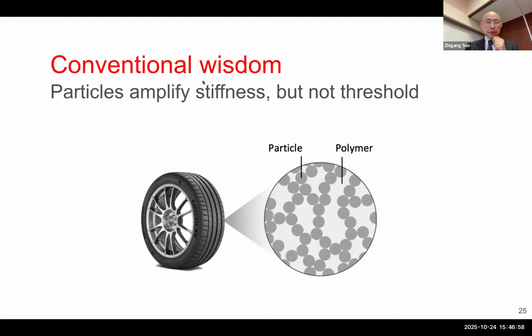So conventional wisdom: the tire is a composite of a polymer and hard particles, typically carbon particles. The particles greatly amplify stiffness, make it stiff. That's true. But not fatigue threshold. People had decades of data to show fatigue threshold stays at about 50, maybe 200 joules per meter squared, not higher.